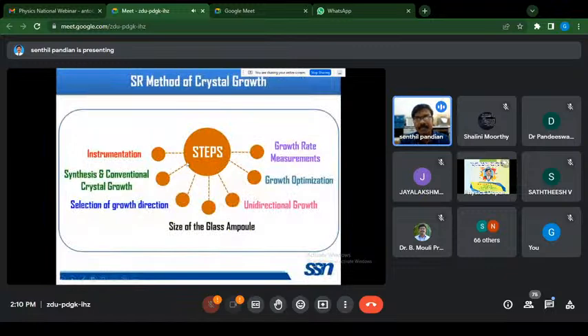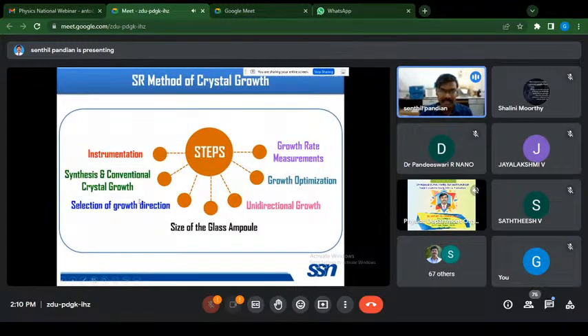So before we choose the seed crystal and the material, we have to carefully optimize all these parameters, that is the instrumentation, synthesis and conventional crystal growth, and the selection of different seed crystal directions, whether we want to grow the A, B, C direction, or if it is a non-centrosymmetric material, we have to select the phase matching direction. If it is a ferroelectric material, we have to go for the polar B direction. And different sizes of the glass ampoule depend upon the solubility of the material and the unidirectional crystal growth.